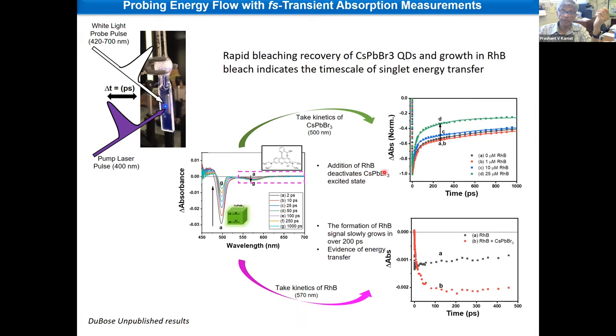On the other hand, if you look into the bleach of rhodamine B, what we see is if you don't have cesium lead bromide, you see the singlet excited state a little bit of trace, and it's flat. But if you add to that cesium lead bromide, now you see a small growth that forms. And you can see the kinetics of this, the growth and the fast decay here. We can get the kinetics. And we know now that energy transfer can occur as fast as 200 picoseconds.